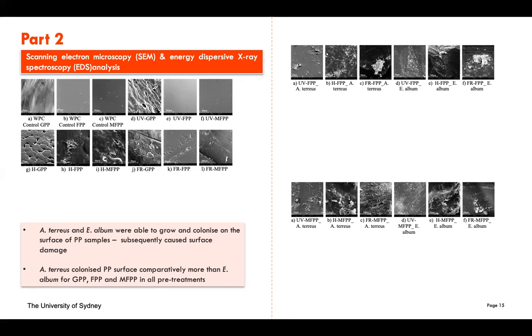Okay, so first, of course, we take the sample from the control. The control was done without pretreatment. So this basically shows nothing. And then we also looked at the surface morphological changes after the pretreatment process. You can see that there is some damage done after the pretreatment. That is what we want, because without the pretreatment, basically the fungi cannot act on the surface or can't even do anything on the polymer.